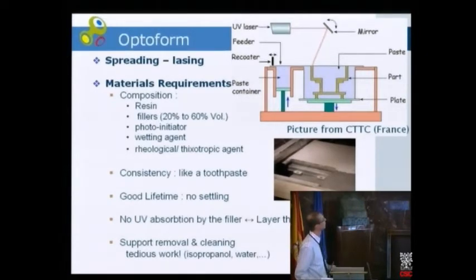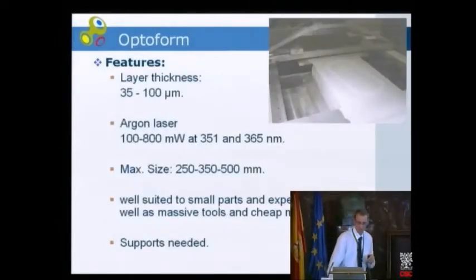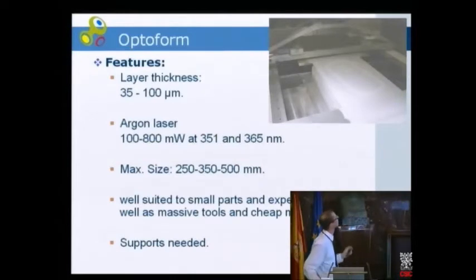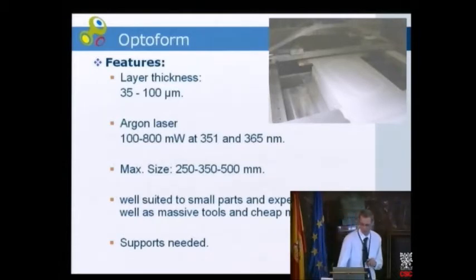So I said we need some support to sustain the part, but after this we have to clean the part. It's very tedious work because the paste is very sticky. It sticks to the part, and we have to remove it manually by using solvents, sometimes organic solvents that are not very healthy, but it's the main drawback of this technology. Different features of this technology are a layer thickness of about 35 to 100 microns. The laser is an argon laser of 100 to 800 milliwatts. The maximum size of the part we can build is a box of 250 by 350 by 500 millimeters.